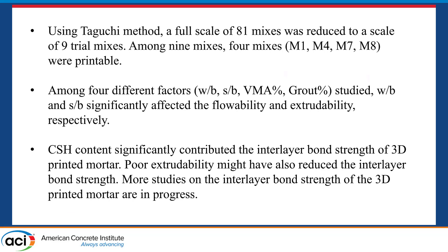In conclusion, using the Taguchi method, only nine mixes were required to investigate the effects of mix design factors on flowability and extrudability. Among nine mixes, four were printable. Water-to-binder ratio and sand-to-binder ratio were the most significant factors on flowability and extrudability, respectively. The C-S-H content significantly affected the interlayer bond strength of the 3D printed mortar, and poor extrudability may have also reduced interlayer bond strength. More studies on interlayer properties are currently in progress. Thank you for listening.